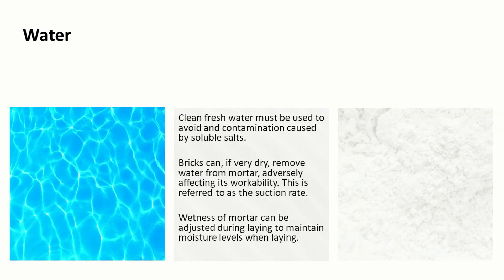Water is the third component within mortar, and it's important that we use clean fresh water, as anything dissolved in the water can cause problems later on. We also need to think about how dry the bricks are. If we're laying bricks in very warm weather and those bricks are very dry, they are going to suck moisture out of the mortar — this is referred to as the suction rate — and that has an adverse effect on the workability of the mortar. We can adjust the wetness of mortar during laying to maintain those moisture levels while we're working it.